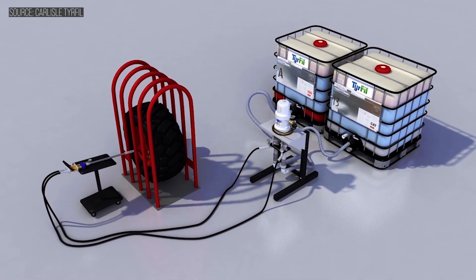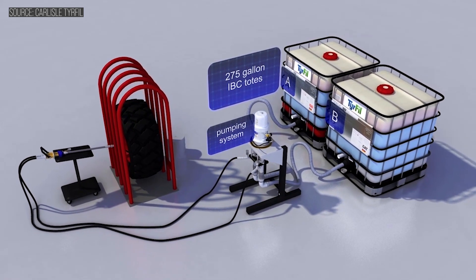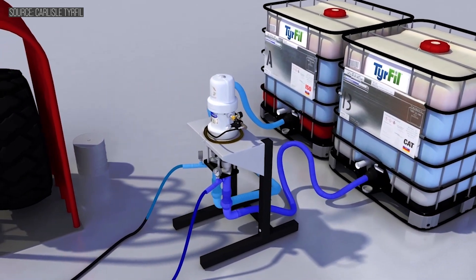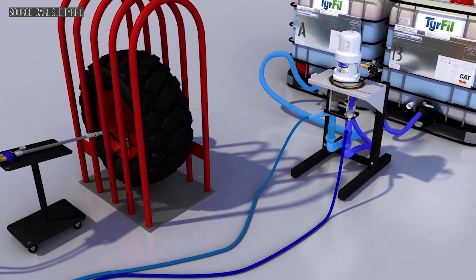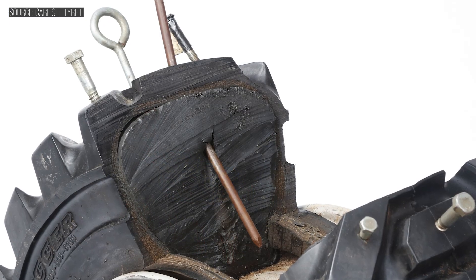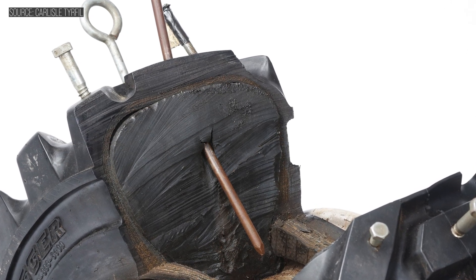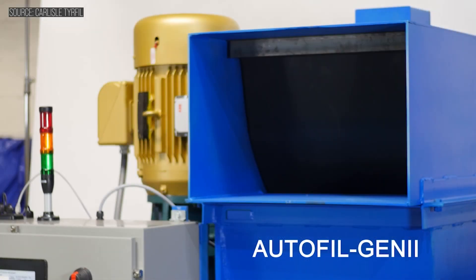This keeps landfills from being filled with used material. The foam is kind of a misnomer — it's not really foam, it's basically an elastomer. An A and B pre-polymer and a catalyst get pumped inside the tire, mixed together, and over 24 to 48 hours this liquid cures into a solid elastomer. When a tire is worn out, the dealer cuts the old tire off, cuts the cured fill into chunks, grinds them up in a recycling machine, and mixes them with virgin material.